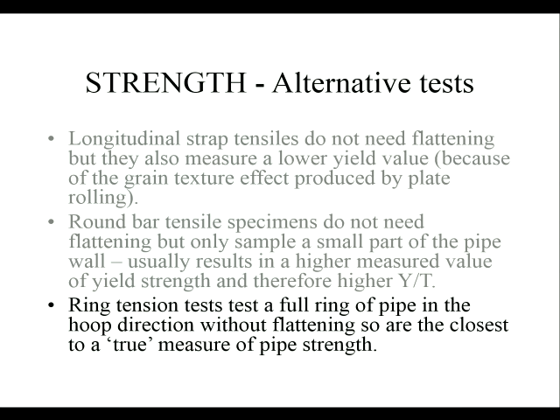What happens if you have to test the whole pipe? Because it's absolutely critical and you don't want to have any Bauschinger effect questions. Well, you do what's called a ring tension test. So you cut a whole ring, a whole hoop of the pipe, put it in the test machine, and then expand that and measure it. And that is the closest we can get to an absolute measure of the pipe behaviour.